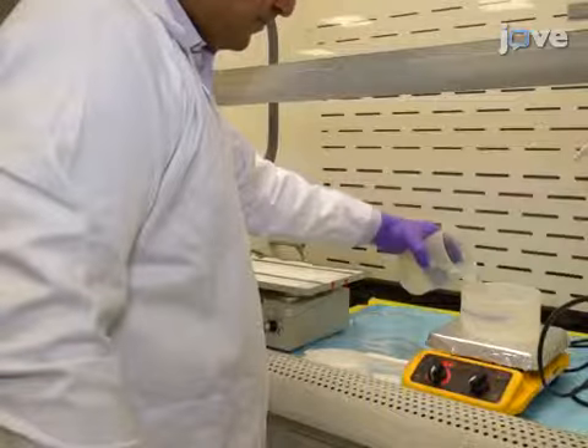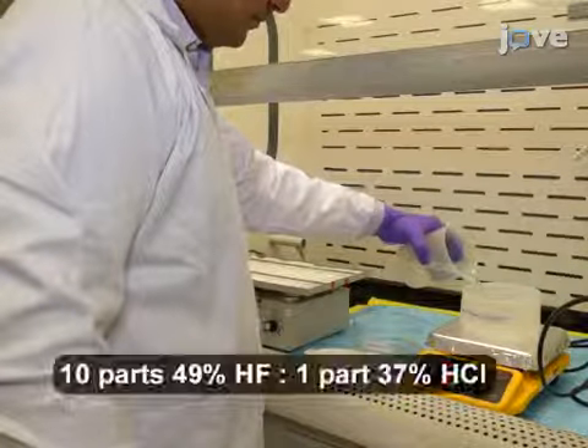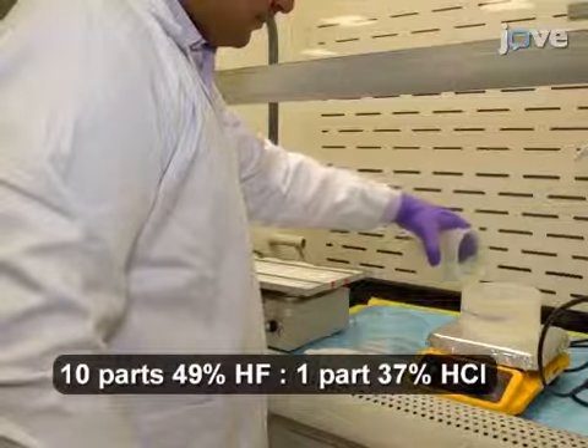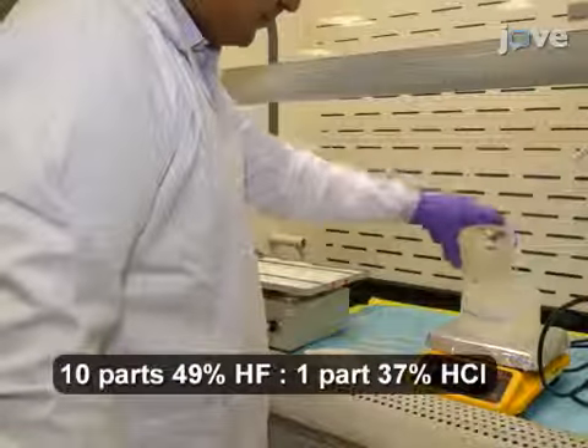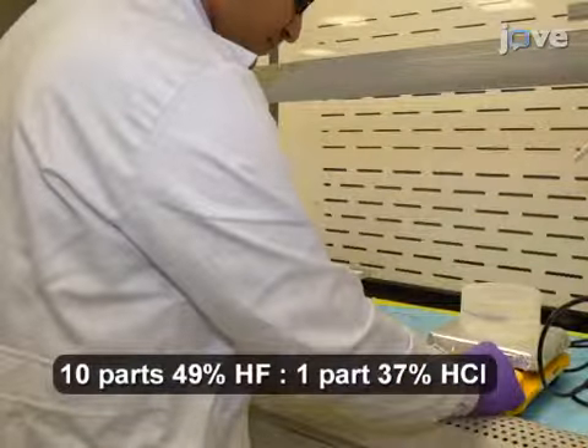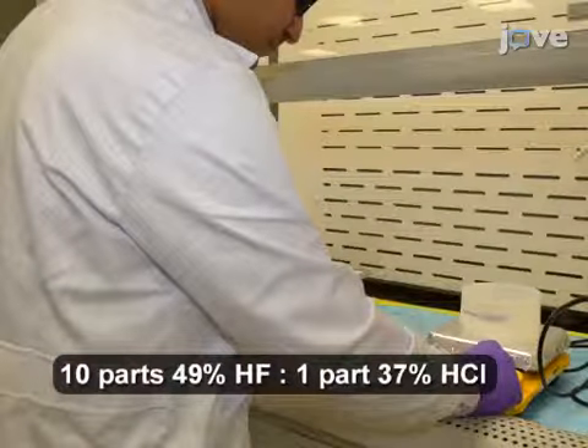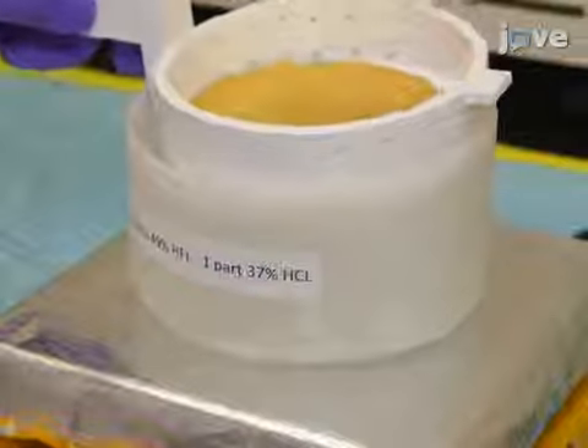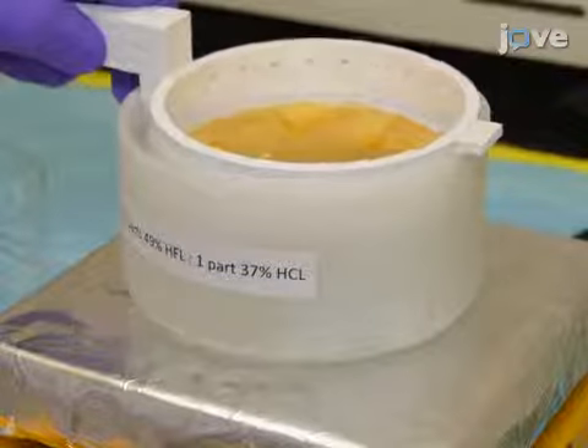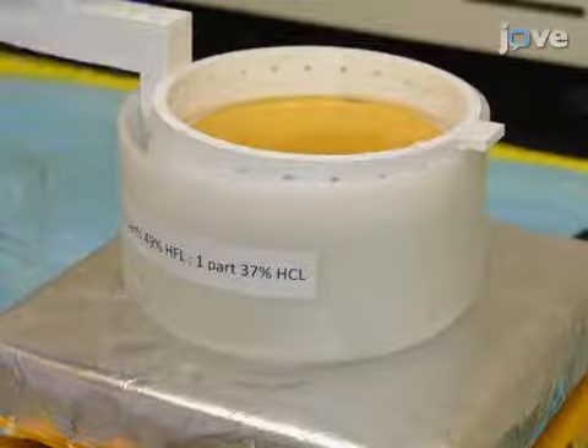Next, prepare a 200 milliliter bath of 10 parts 49% hydrofluoric acid and 1 part 37% hydrochloric acid in a plastic container with a magnetic stirrer. Add the sample and etch the microlenses at a rate of 7 micrometers per minute for 8.5 minutes while stirring.